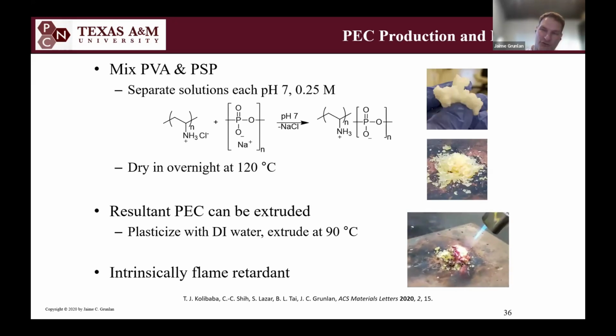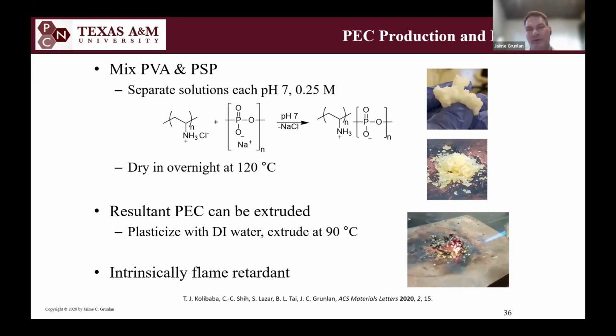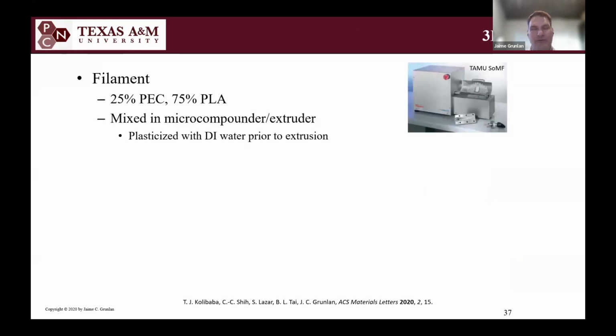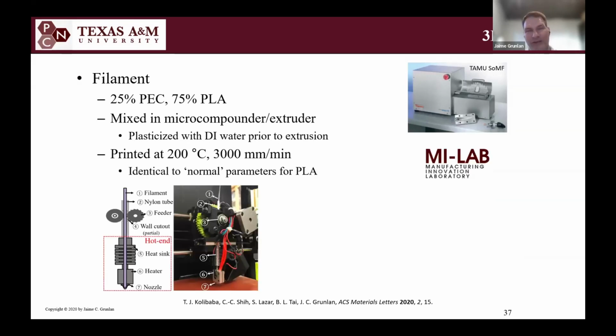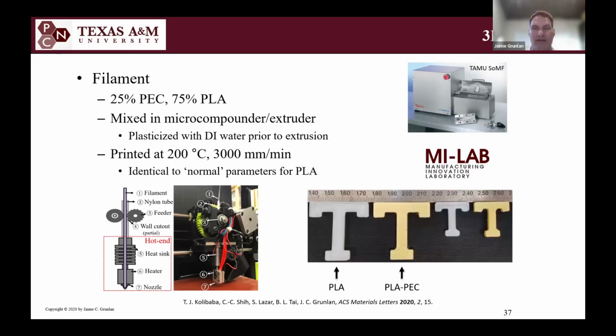And when I torch the dried PEC powder, you can see how much it intumesces when it's torched there. So this is a very intumescent additive. And so we made a filament with 25% of the complex and 75% PLA. By the way, it has all the same mechanical properties. We did DMA, dynamic mechanical analysis, and it prints the same way. We use the same printer to print pure PLA, 100% PLA, and then this 25-75 FR filament.